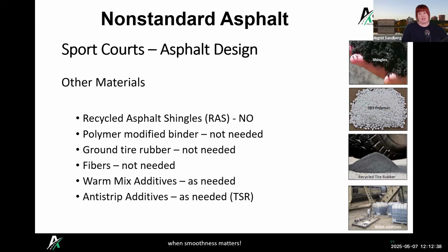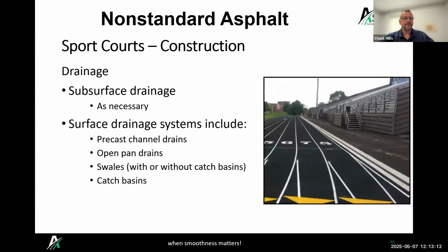So we got a question in the chat. So no RAP, all limestone aggregates for a sport court asphalt. Is that for the top course? Yeah. If you're doing two courses, like if you're typically placing about 3 inches thick over 6 inches of aggregate base or something like that, if you're doing your leveling course, you could allow some RAP in that. But typically, most of our producers here in Michigan have that special mix design that's 100% limestone, no RAP for the top course. Awesome. Yep. Good question.